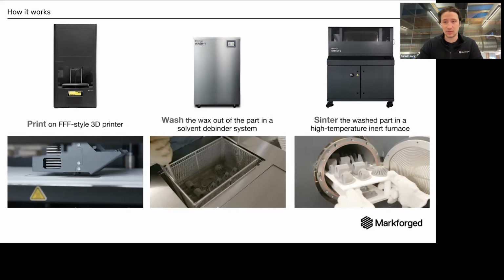The way that works is we basically use MIM feedstock, if you're familiar with metal injection molding, and that feedstock is metal powder that's encased in a polymer and wax binder. It's a 2-part binder. The effect is that this filament is actually kind of waxy and roughly polymer-like, although it's not very similar to any polymer that you conventionally 3D print with. It's printable through an FFF system.